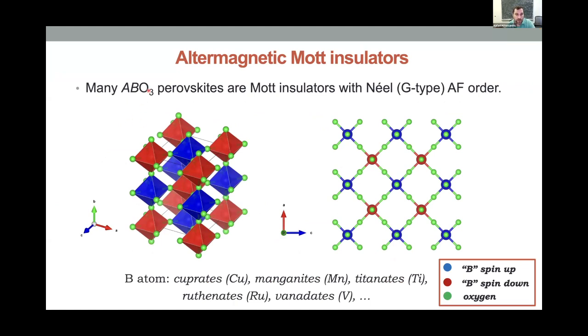Okay, so I think, and this is already pointed out in different contexts, but these perovskites ABO3, most of them are Mott insulators, right? They have Néel type or G-type antiferromagnetic order with alternating spin up and spin down. This comes again from essentially Mott physics. And in the ideal perovskite structure, which is cubic, it's really antiferromagnetic order with the spins up and down, as I'm pointing here. The green are the oxygen, okay?